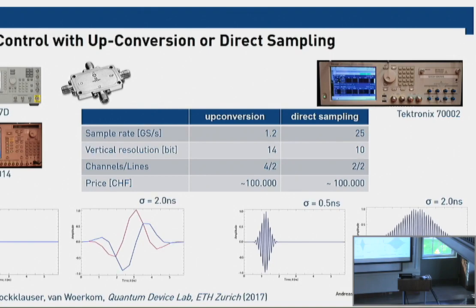So you can do rather sophisticated pulse shaping directly on the individual amplitudes and phases of the microwave field that you apply to your circuit. And that was actually quite useful for us for these relatively short pulses. So you see a pulse with 2 nanosecond sigma or so, but still we managed to